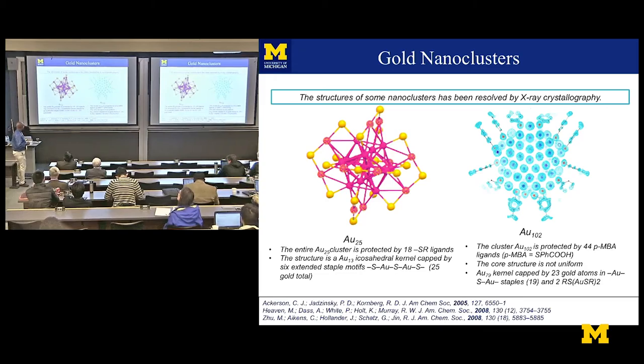All right, so the important ones that people spent a lot of time trying to understand from a chemical standpoint was this structure. It's a very strange structure. So it has 13 atoms in the middle, and then the rest of the gold atoms are in this staple geometry of gold, sulfur, gold on the outside. They call it a staple, okay? These gold-sulfur bonds are stapled to the outside, kind of hovering over the 13 core atoms, okay? And then the gold 102 has a much more core-shell structure to it. But a lot of people spend a lot of time on this gold 25. And so we said, well, we're really interested in the optical properties.